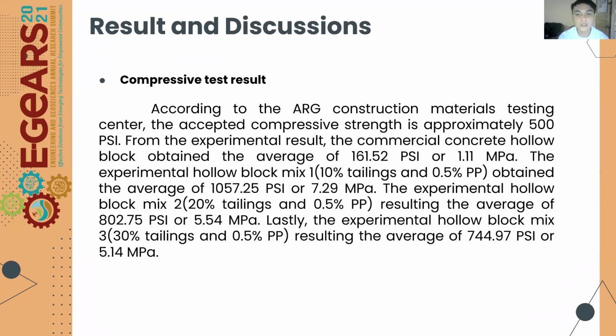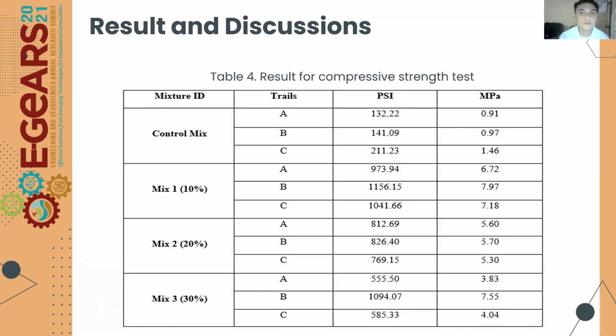Lastly, the experimental hollow blocks mix 3 with 30% tailings and 0.5 polypropylene plastic resulted in the average of 744.97 psi or 5.14 MPa. So this is the result of the compressive strength test.